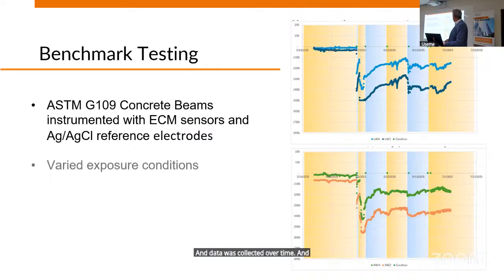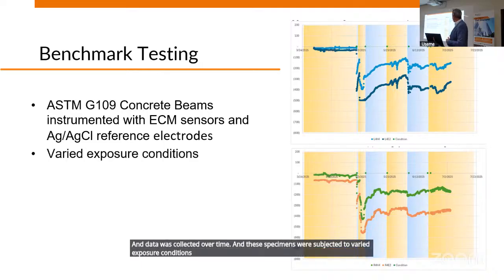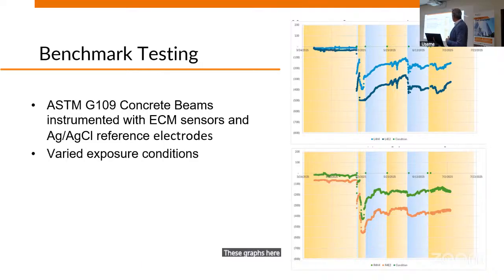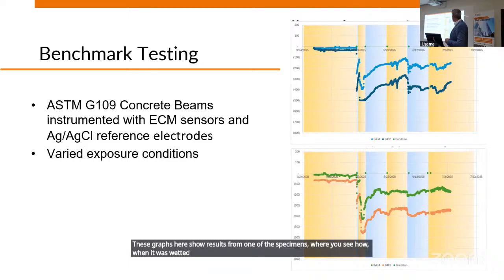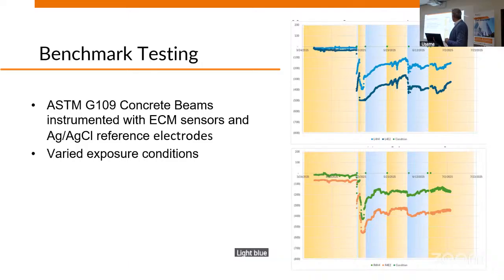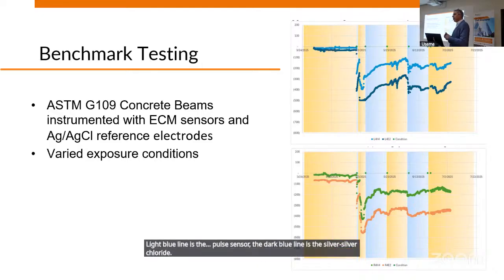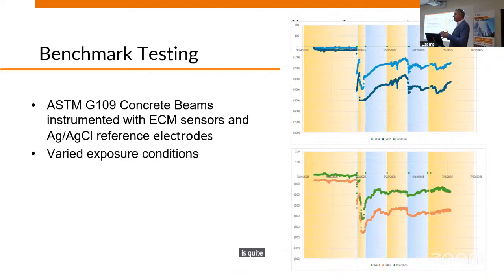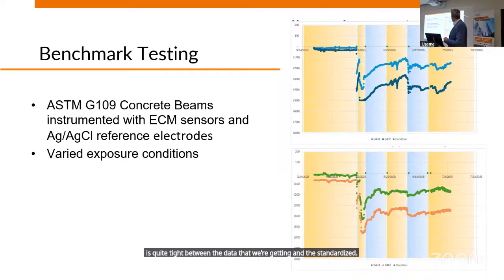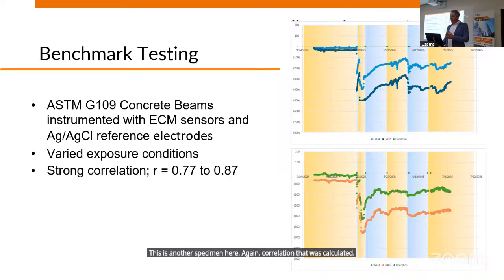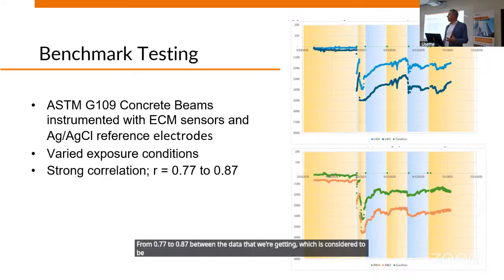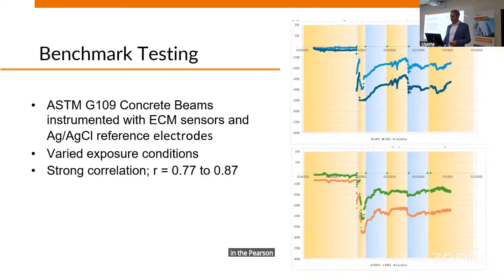And these specimens were subjected to varied exposure conditions, wet and dry. These graphs here show the results from one of the specimens, where you see how when it was wetted, potentials start shifting. The light blue line is the pulse sensor. The dark blue line is the silver chloride. And you see how the correlation is quite tight between the data that we're getting and the standardized. This is another specimen here. Again, the correlation was calculated from 0.77 to 0.87, which is considered to be strongly correlating in the Pearson correlation methodology.